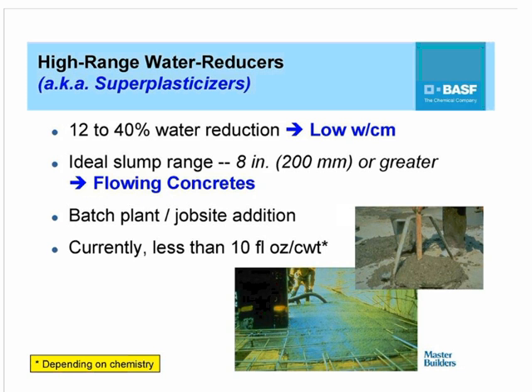The ideal slump range for most of these materials will be 8 inches or greater. And they can be added either at the batch plant or at the job site. Initially, when these materials were developed, based on the first generation, second generation type technologies, they were based on lignosulfonate salts, which had very short pot life. And as a result of that, job site addition was a preferred method of using these materials, because once they were added to the concrete and mixed into the concrete, then the concrete could be placed right away.